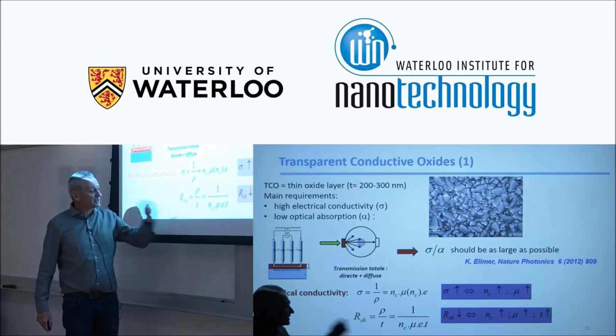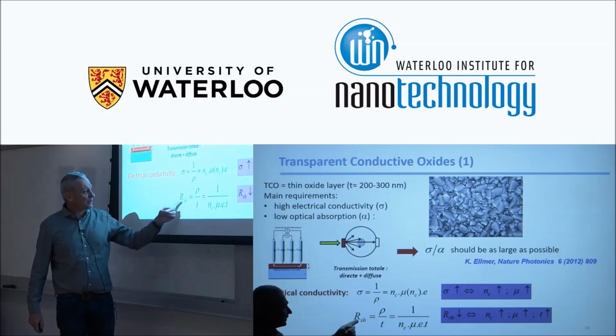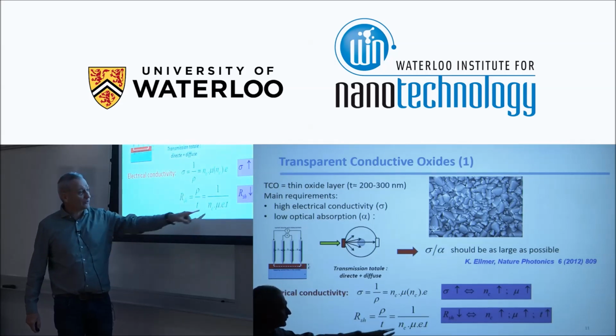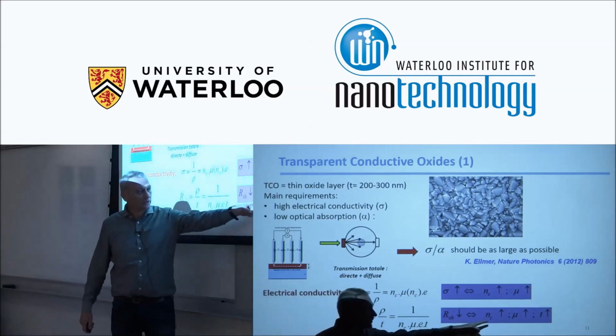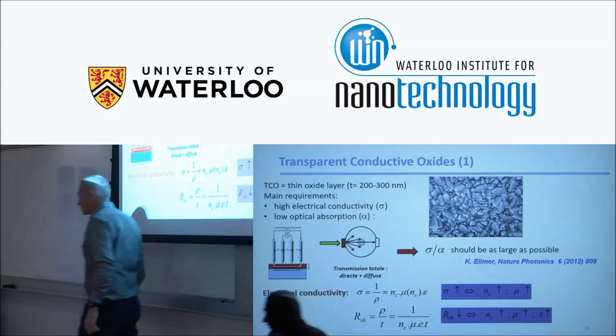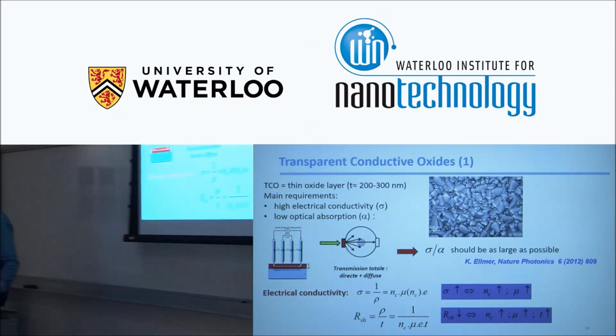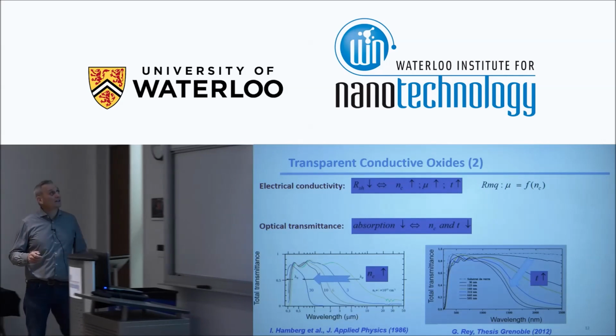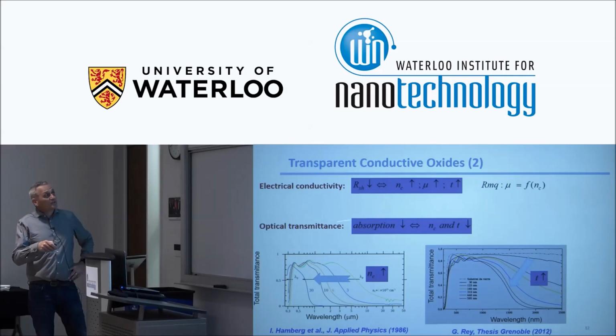And if we want the sheet resistance to be as low as possible, this is our resistivity divided by thickness. That means we have to increase the carrier density, to increase the mobility, and to increase the thickness of the layer. That's the way to increase the electrical transport. But for the optical transparency, if we want to decrease our absorption, we have to decrease NC and we have to decrease the thickness. This is illustrated by these two curves here.